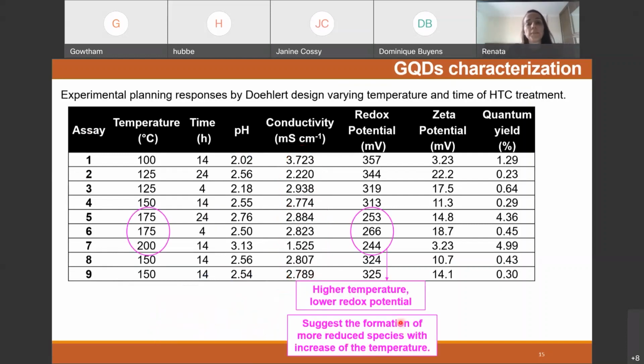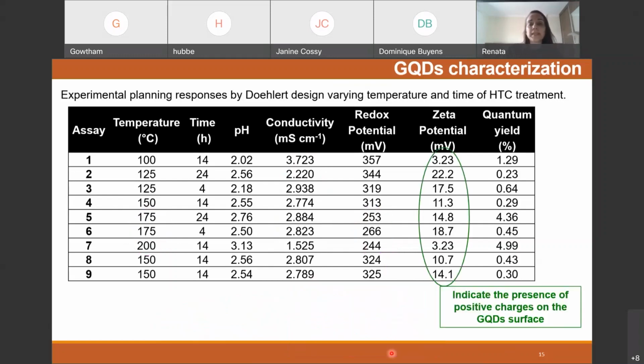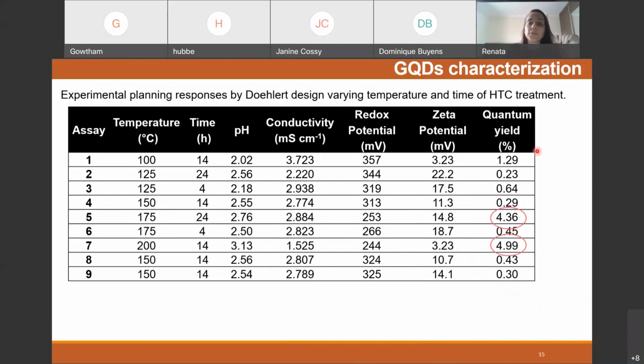About the redox potential, it is possible to observe that high temperature produced a smaller redox potential. This result suggests the formation of more reduced species with the increase of the temperature. The zeta potential was evaluated too, and it was positive, and these results suggest the presence of positive charges on the graphene quantum dots. About the quantum yield, the results were similar to those obtained in the literature, but highlights for SA5 and SA7, which used the high temperatures and obtained the bigger results for quantum yield.